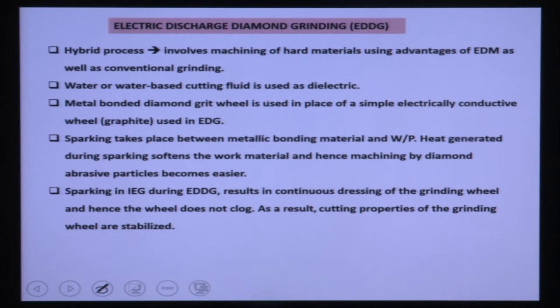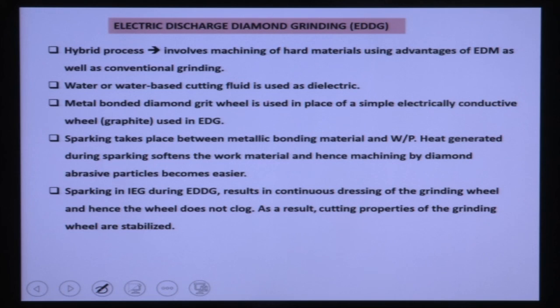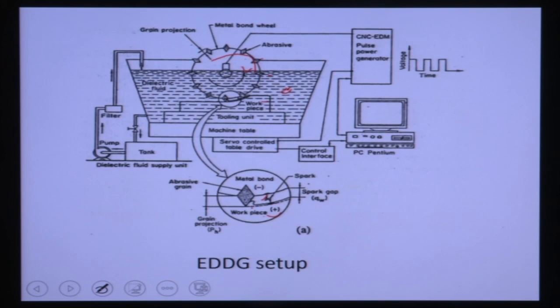So this sparking occurs, and machining occurs in the workpiece, as well as sparking in the metallic bonded grinding wheel also. So dressing of this grinding wheel also occurs simultaneously. So no separate dressing operation is required during electro-discharge diamond grinding. There is a continuous dressing of the grinding wheel, hence the wheel does not clog. As a result, cutting properties of the grinding wheel are stabilized, and uniform grinding operations are maintained.